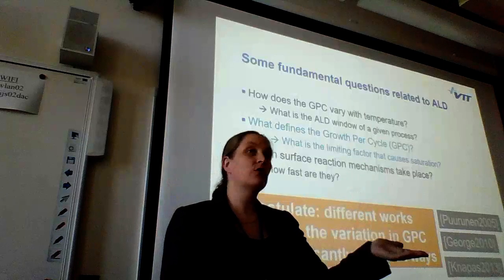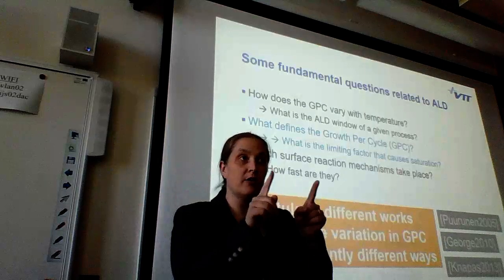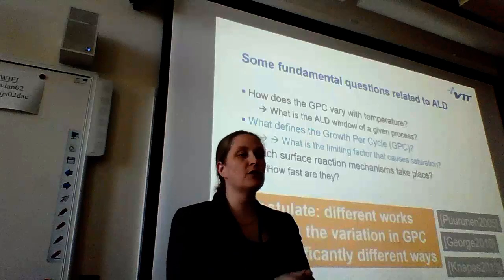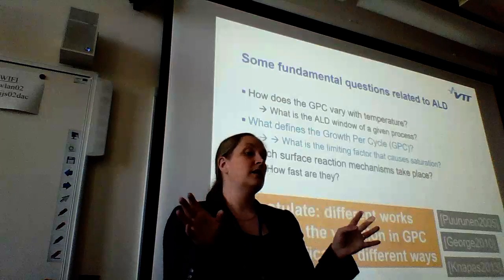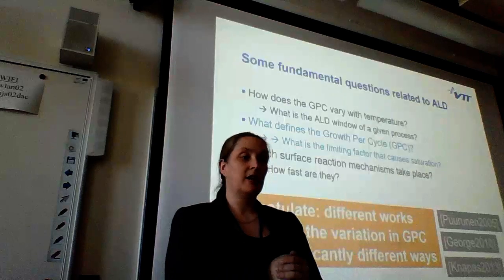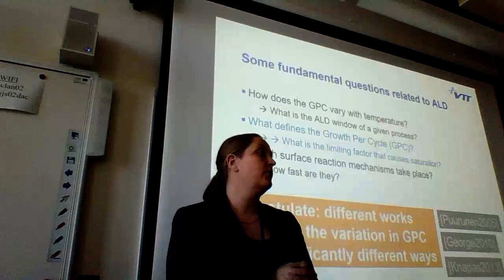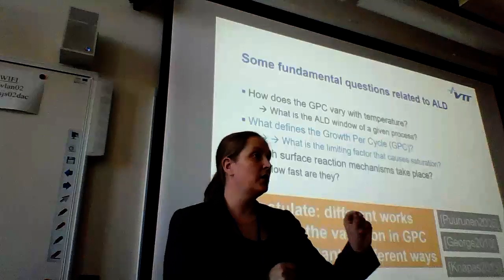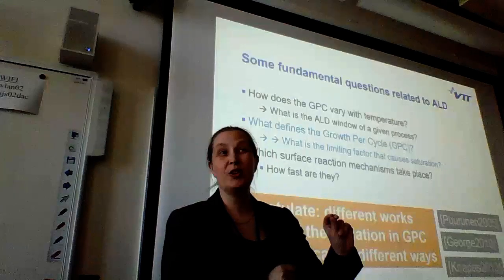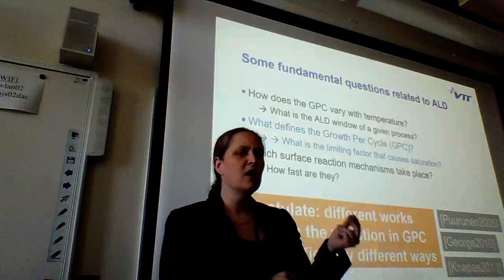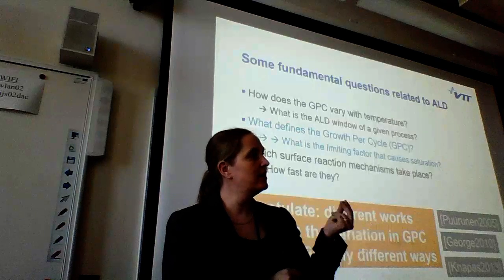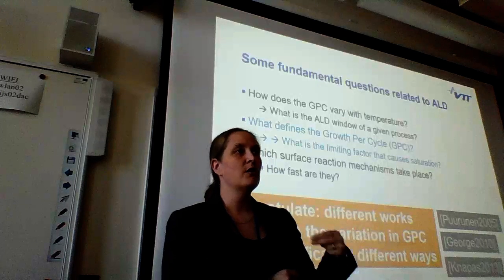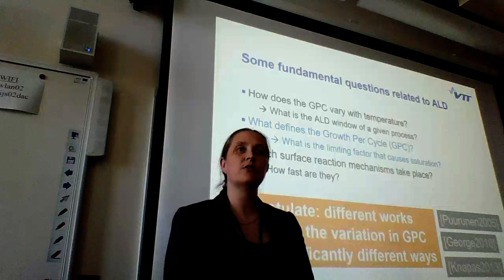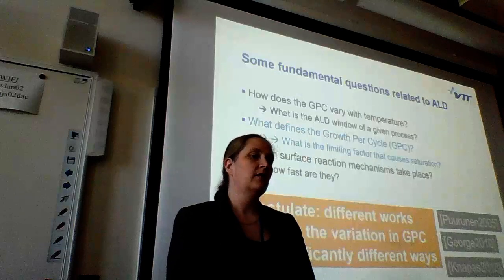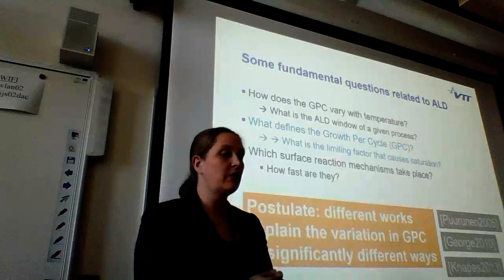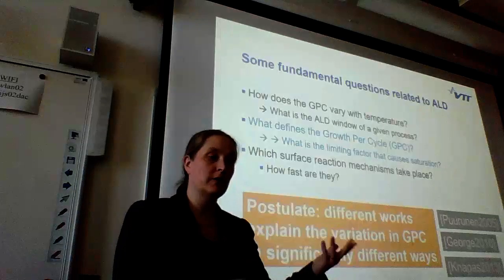TMA water you can use at room temperature up to 300. Some have a very, very narrow window of some tens of degrees or so. And to me, this has always been puzzling. What defines the growth per cycle? Why do we get this number that we get? It should be, and often is, reactor independent. It's defined by nature. What is it? What's the limiting factor that gives us this exact number? What's the thing that causes saturation to take place at that level? And which surface reaction mechanisms take place and how fast they are, if you go to kinetics.